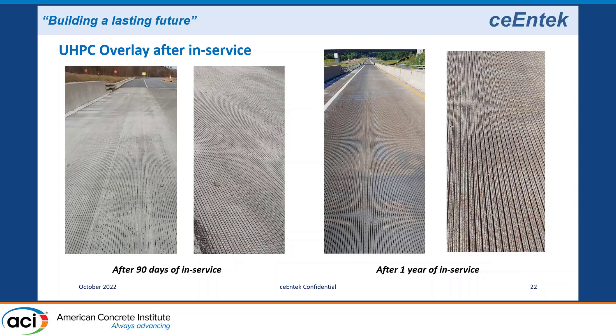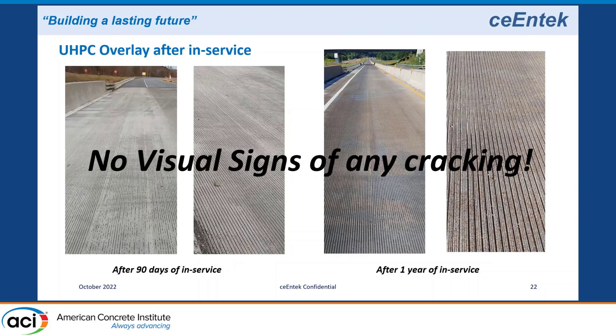Over the abutment, where the overlay crossed into the negative bending moment region, I could not see any cracks visually under normal conditions. However, one morning after rain I walked it again specifically to check over the abutment and could see a little bit of micro-cracking over the abutments — which you would expect in a negative bending region. So basically there were no visual signs of cracking, with the caveat of some micro-cracking over the negative bending region.